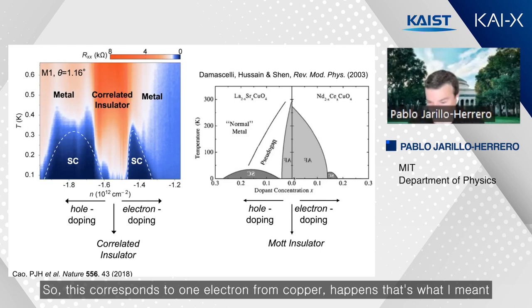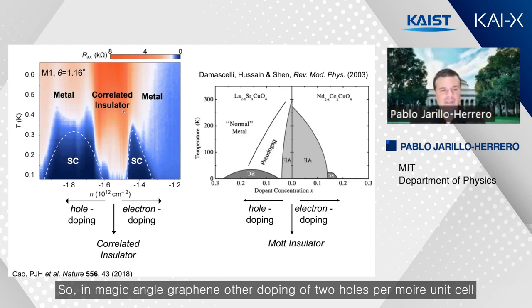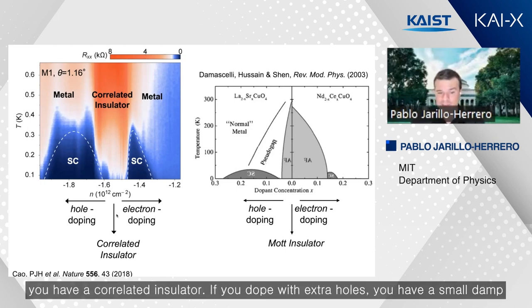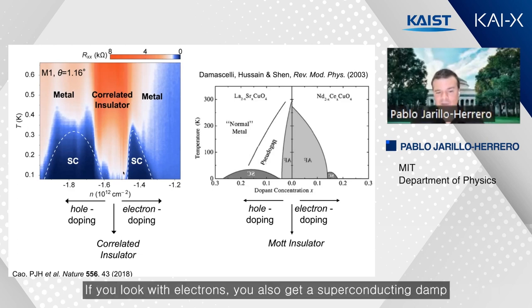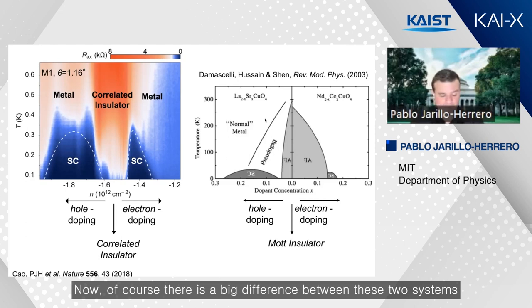So this corresponds to one electron per copper atom, is what I meant, electron hole. So in magic angle twisted bilayer graphene, at a doping of two holes per moiré unit cell, you have a correlated insulator. If you dope with extra holes, you have a superconducting dome. If you dope with electrons, you also get a superconducting dome.